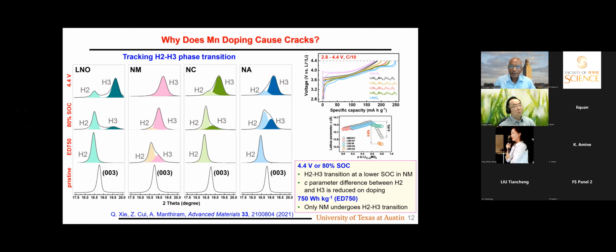The only thing I can say is these will make a lot of changes in the bonding, particularly when you have nickel and cobalt, they will have the 3D band a little bit broader. When you go to manganese or aluminum doping, they may introduce a little bit of localization, because they are not transition metals, they have edge-shared octahedra, the electron hopping will be a little bit disturbed, because manganese and aluminum will act as speed breakers. So that can cause the so-called Anderson localization, which the physics community knows. It may introduce impurity levels, narrowing of the band, so they may have consequences. So I do not have any direct answer for you, but I can very well understand the changes in bonding can cause these kinds of problems. There is no reason they have to occur exactly at the same place, because there is a lot of chemistry changing when you dope.